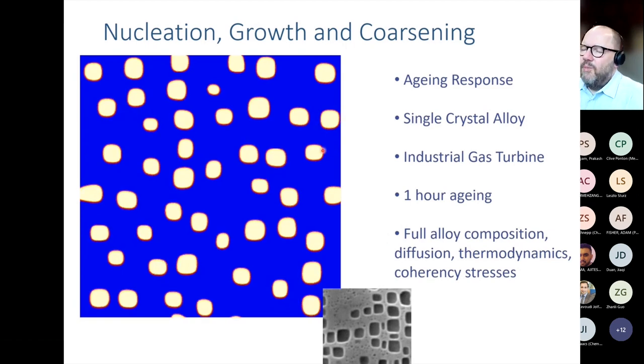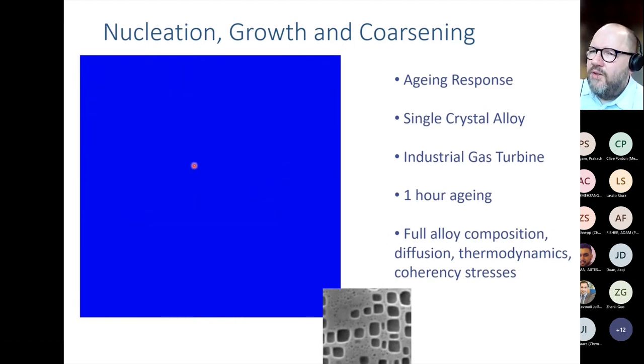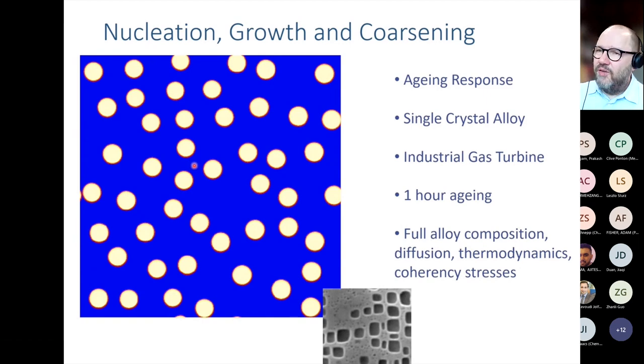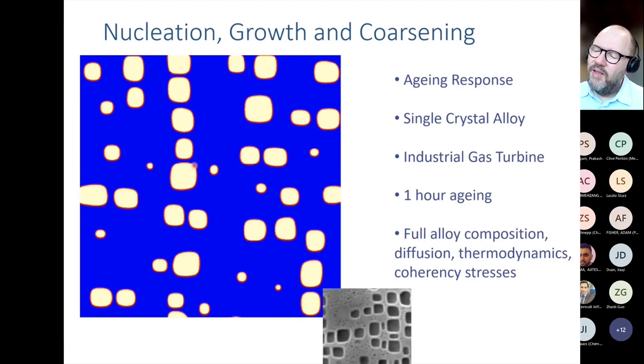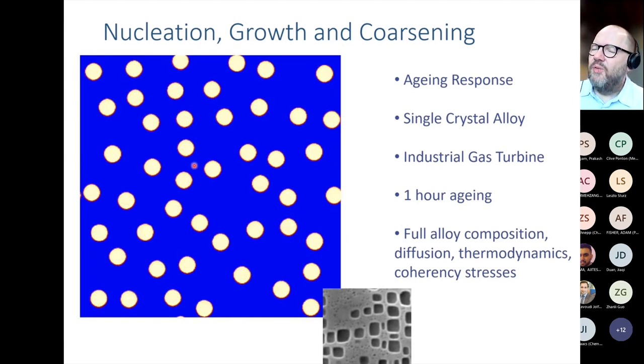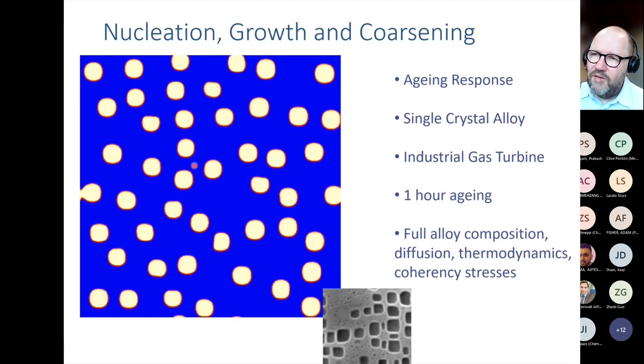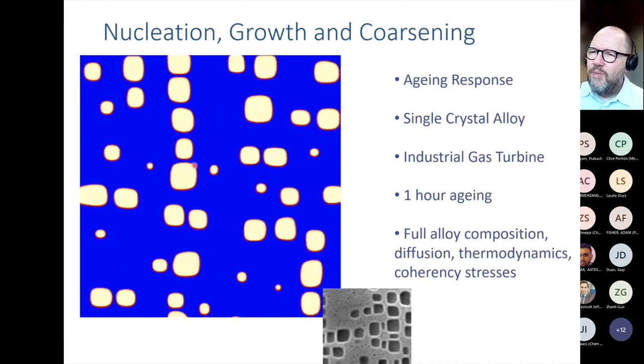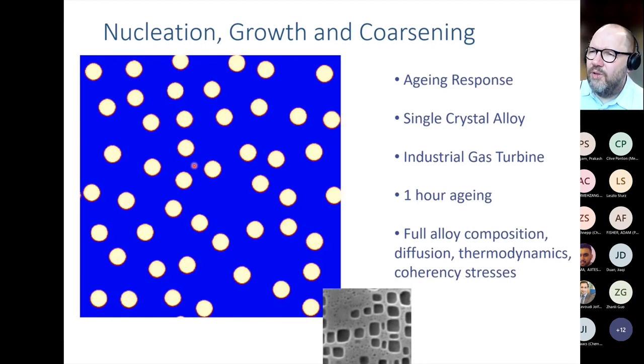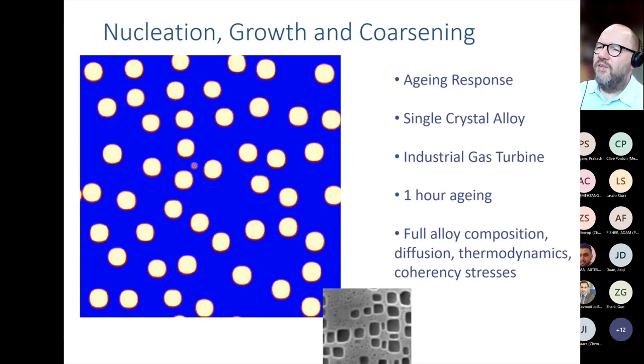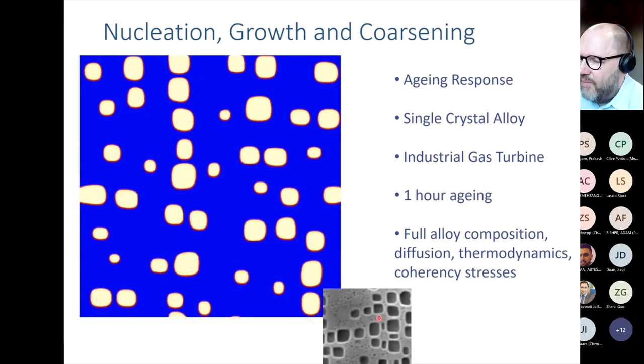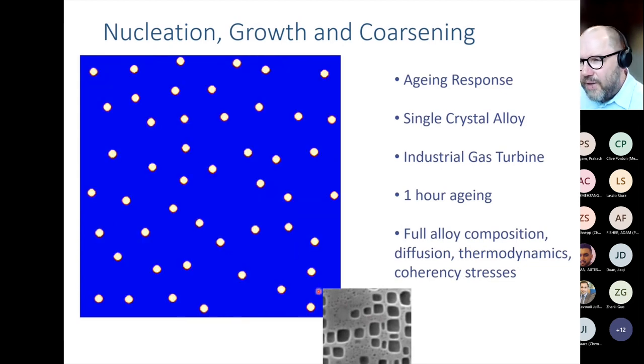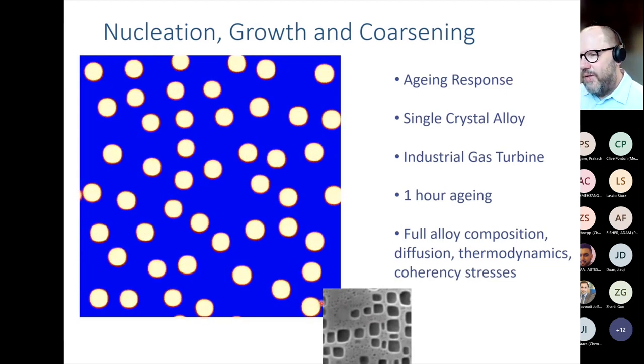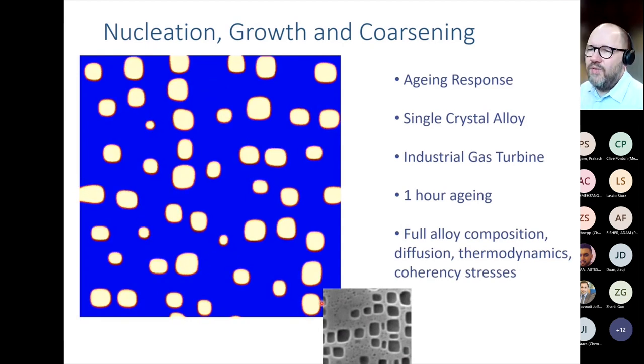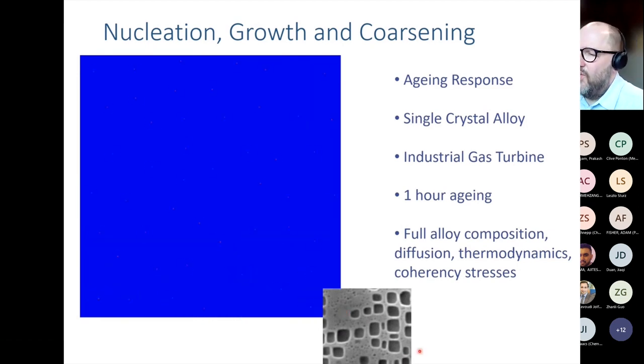So we find that initially gamma prime is forming, nucleating, growing, and as the particles grow, they build up a stress field due to coherency difference in lattice parameter between the gamma and the gamma prime phase. And that stress field actually causes the gamma prime particles to align in rows and columns, so that we end up with this brick and mortar type structure that we normally see in the micrographs as well. But it takes time to develop. And down here is a micrograph, so it's a rather qualitative comparison, I admit, but we find that the final structure shows a very similar appearance to the one we see in the micrograph.